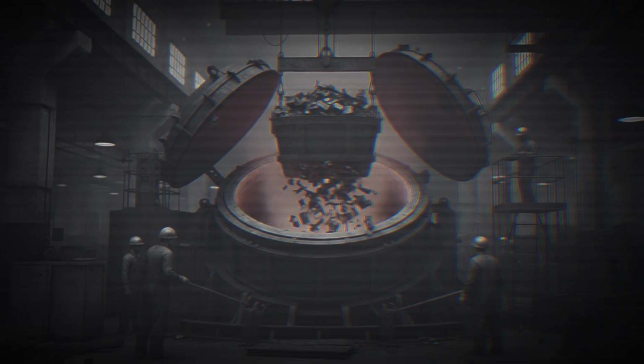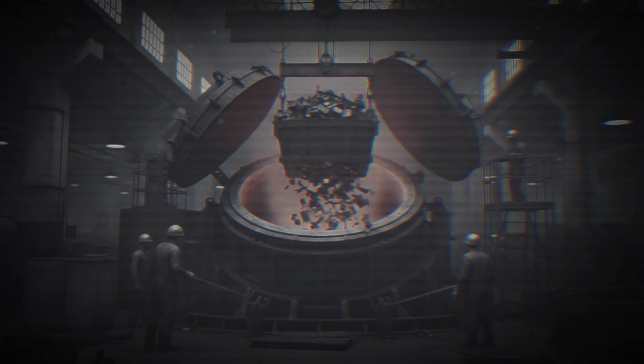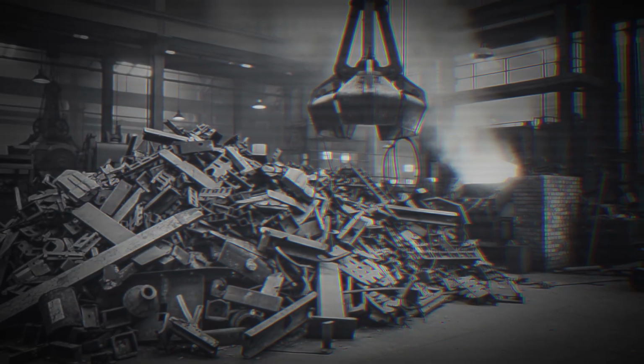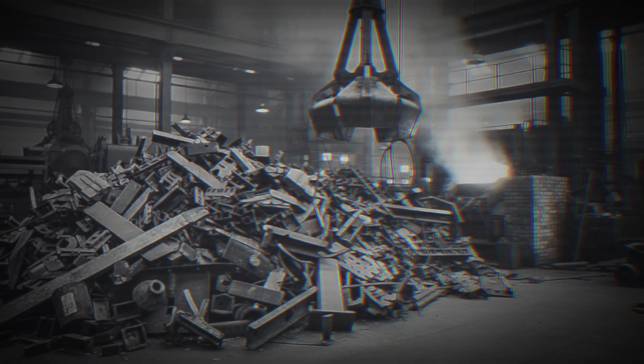Here is the engineering paradox. The furnace was most efficient and most profitable when running continuously. Every shutdown cost money and lost production, but the furnace degraded continuously through use. Running it longer between maintenance intervals maximized short-term output and increased the probability of catastrophic lining failure. Lining failure, a full breakthrough where liquid steel breached the hearth and flowed out of the furnace structure, was not a minor maintenance problem. It was an emergency.